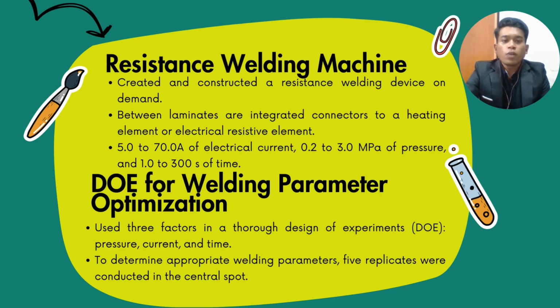Thirdly is the resistance welding machine. Create and construct a resistance welding device on demand. Between the laminates are integrated connectors to a heating element or electrical resistive element. Require 5 to 70 ampere of electrical current, 0.2 to 3 megapascal of pressure, and 1 to 300 seconds of time.